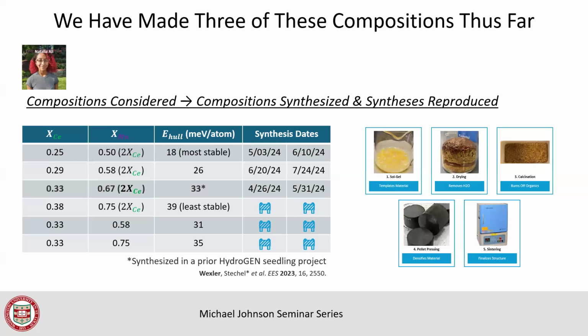They made different batches. You can see here on the right, this shows these materials being made. It's made through a solution phase process. It's kind of like a liquidy goop. You heat it up and it reacts and the atoms rearrange to form our crystal. Then it forms what has been, I think, fairly accurately described as the souffle, which is when it's been dried. So this is the material after it's finished cooking. And we dry it off. We do a process called calcination. Calcination basically means that we heat it to high temperature. And what happens is there's enough energy for the atoms to jiggle around and fall into better spots, where they form more bonds with other atoms. So it's a way of nudging the atoms into their ideal situation in the crystal.